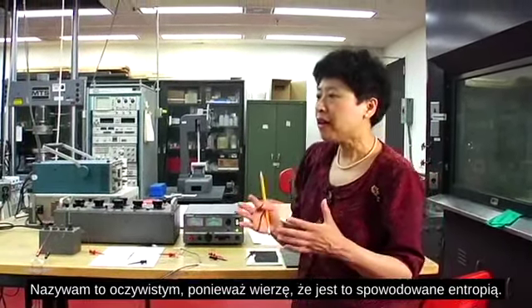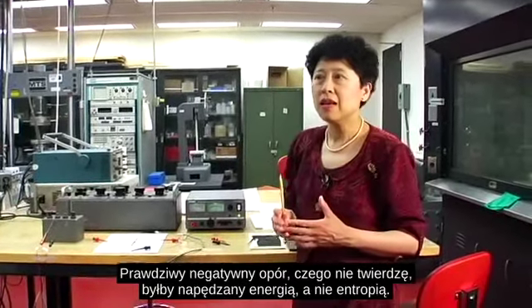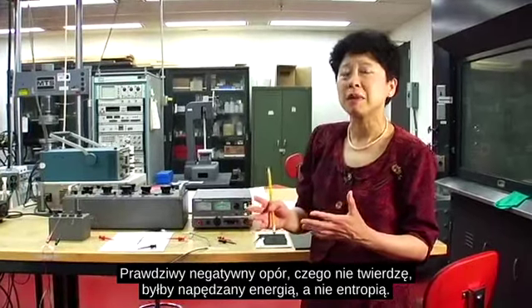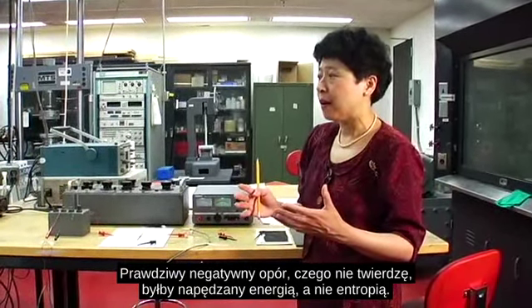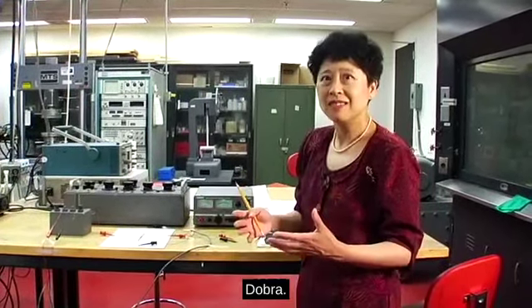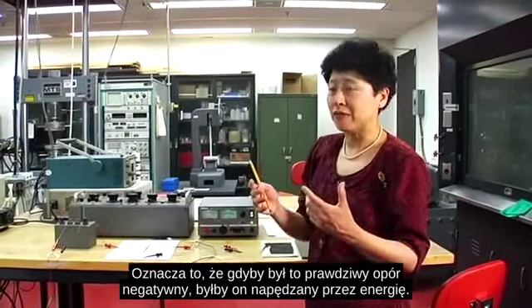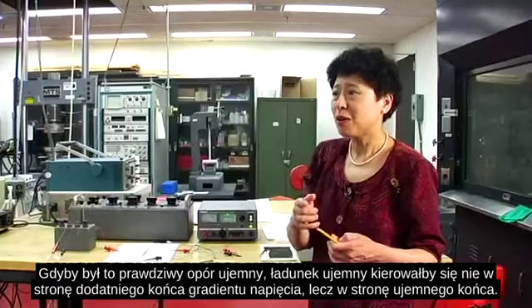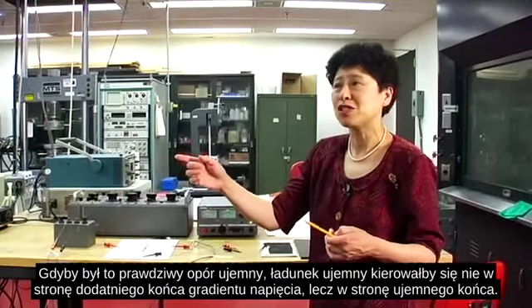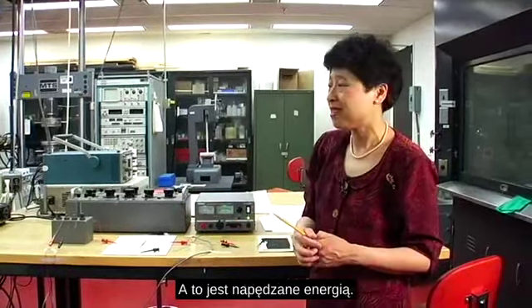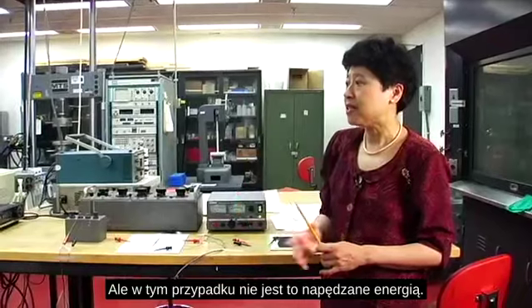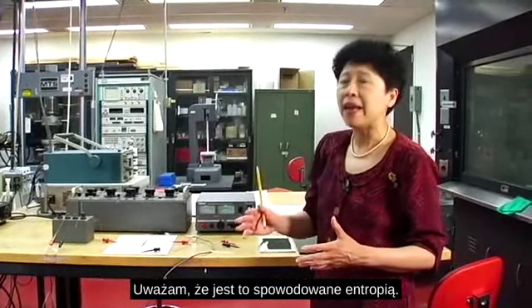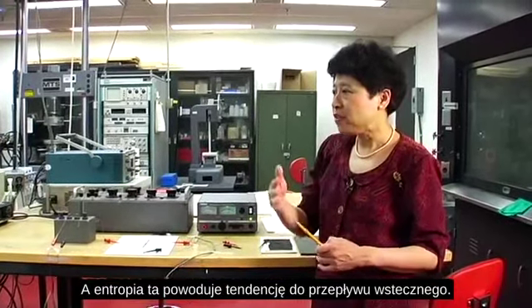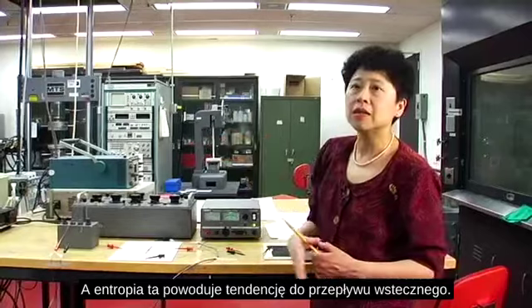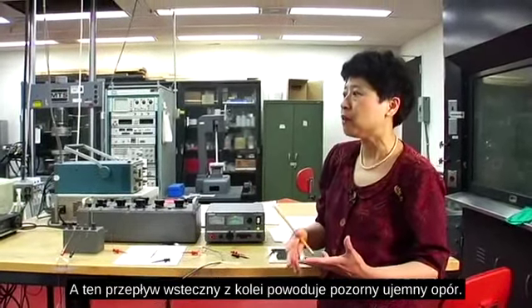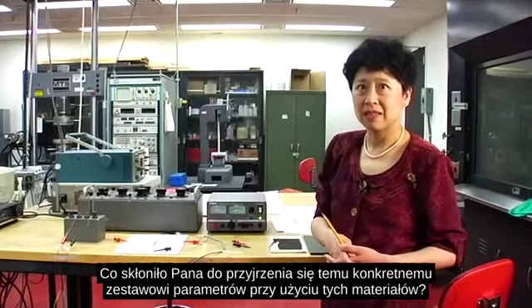So I call it apparent because I believe that it's entropy driven. True negative resistance, which I'm not claiming, would have been driven by energy rather than by entropy. That is, if it were true negative resistance, a negative charge would go toward not the positive end of a voltage gradient, but the negative end. That would be true negative resistance, and that's driven by energy. But in this case, it's not driven by energy. I believe it's driven by entropy. And that entropy causes the tendency for backflow, and that backflow in turn results in the apparent negative resistance.